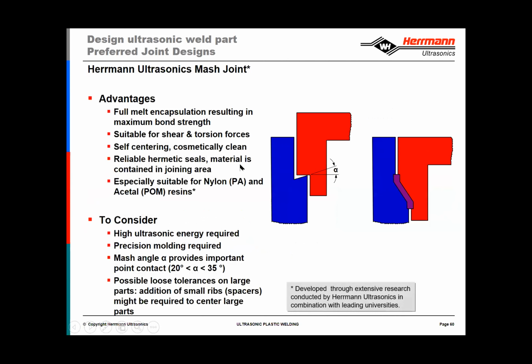In some cases, especially for semi-crystalline materials, we've developed the mash joint. It's a variation on what you may have seen from a typical shear joint. What we've done is to add a slight angle here. In the more traditional shear joint, this would be a flat area, and therefore it does not allow point contact. Again, initiating the melt with point contact is a requirement. What we see after the welding is that the melt is contained within the parts. We still get that shearing effect of the red part into the blue part, but the angle is what's important to note here.